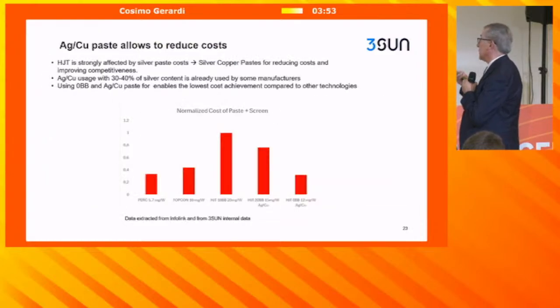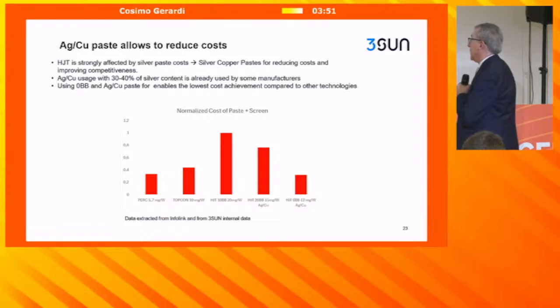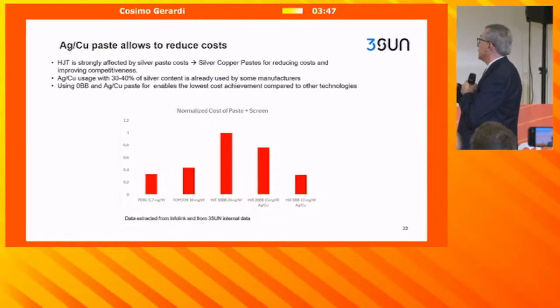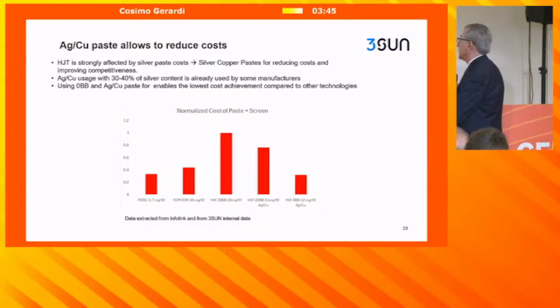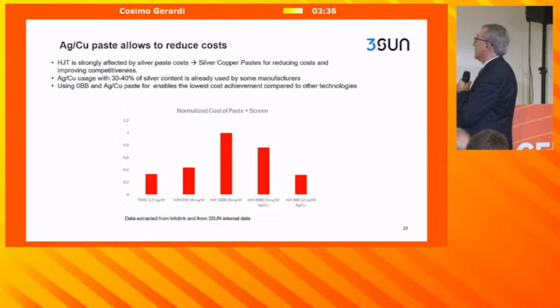For example, using a silver copper paste and a zero bus bar approach, it is possible to reduce the usage of silver in terms of milligrams per watt, and heterojunction can reduce the gap or even be more competitive than TOPCon, that today has less consumption of silver.